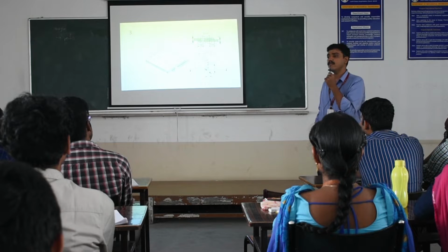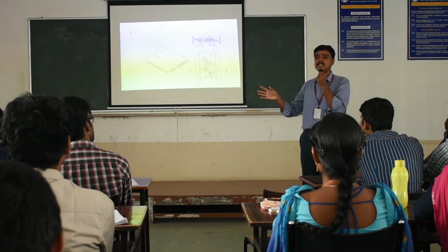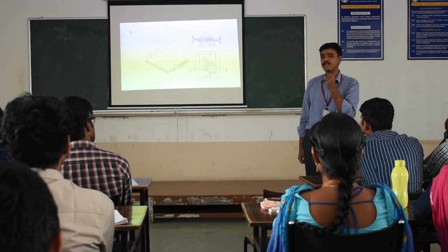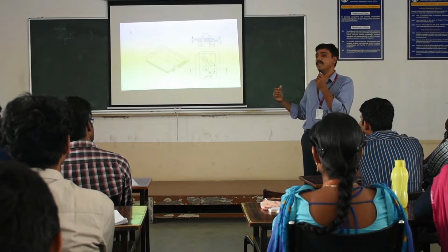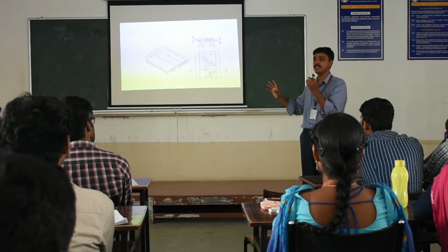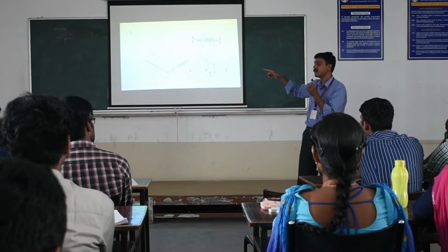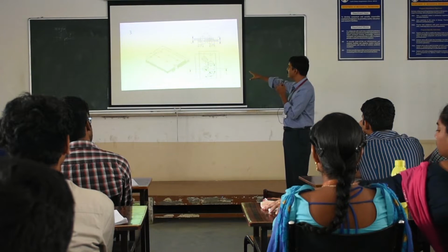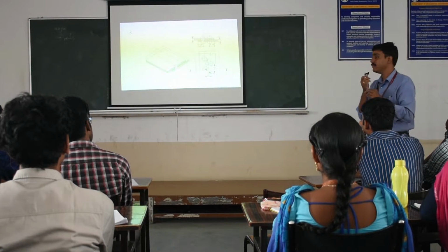Now, this technology or this system was evident after a few shipwrecks. The most common, or most infamous I would say, is the shipwreck of the Titanic, where there are many reasons why ships fail, specifically why the Titanic failed. One is because of a ductile-brittle transition: the metal changed from a ductile material to brittle. Second, they used much heavier, much bigger rivets and tried to fix them in a smaller space, which in turn caused a huge amount of stress concentration, and it broke. In many areas it broke exactly at the rivet joints. So we go for some difference or some kind of zigzag system to avoid those kinds of failures.